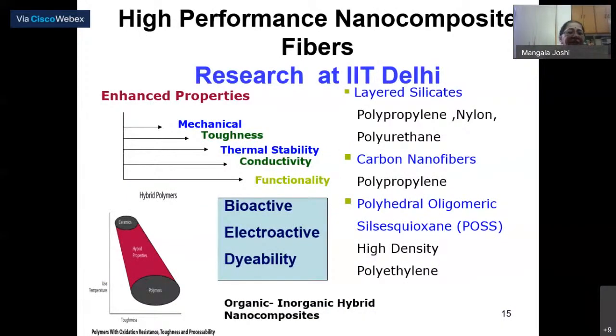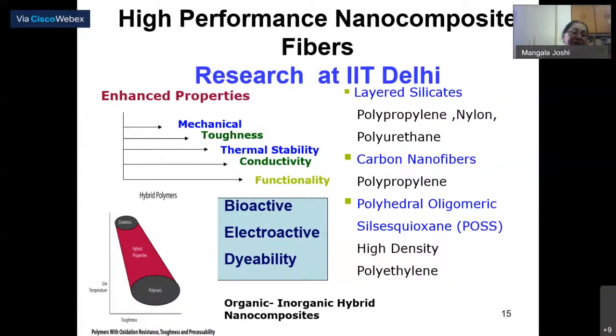In this area, we in textiles know fibers are very important. Fibers are the basic units of textiles. There are many synthetic fibers which are made by melt spinning or solution spinning. So we started working on nanocomposite fibers, and we were looking at enhancing properties like mechanical properties, tensile strength and modulus, toughness, improving the thermal stability of the polymer, and improving the conductivity, whether electrical or thermal. Now we are looking at imparting functionality like bioactive properties or electroactive properties, or improving even the dyeability. We have worked with polymers like polypropylene, nylon, and polyurethane with layered silicates as nanomaterial. We have worked with carbon nanofibers, and with POSS, which is a three-dimensional hybrid inorganic-organic nanofiller. Most of my research has gone into this.